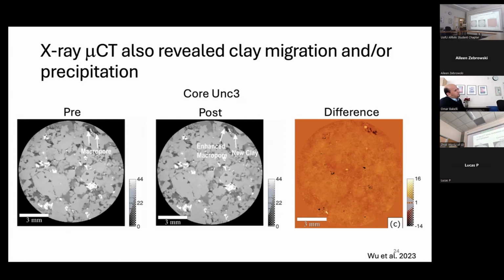That means enhancement of macro pore. So that pore opened up a little bit, which means some clay mineral dissolved. Even if this one doesn't have much clay, we think that the clay dissolved. But here, there is some lighter color mineral forming, and that's a new clay we found. So there's some clay dissolution, and then there's some clay reprecipitation, or even migration. It might have always been there, but with the flow, it changed location to an adjacent location. So we definitely see a reprecipitation of some iron oxides. And this plot shows pretty much the difference between these two.